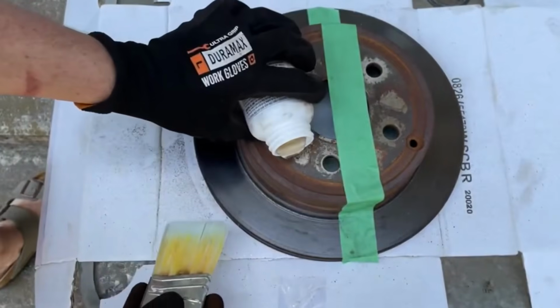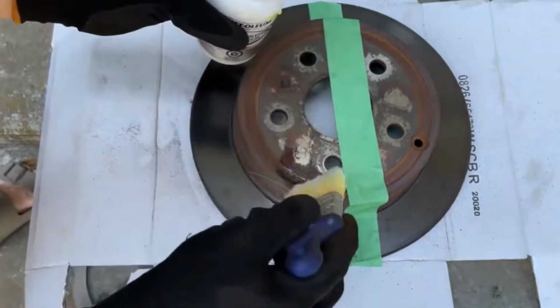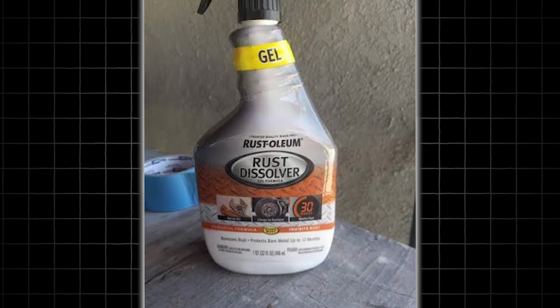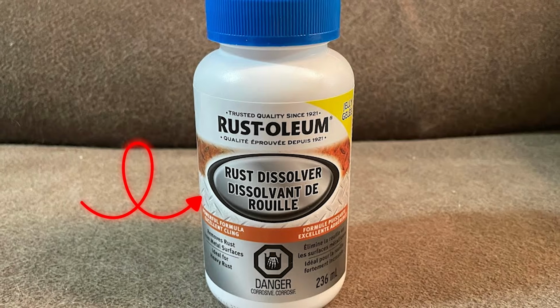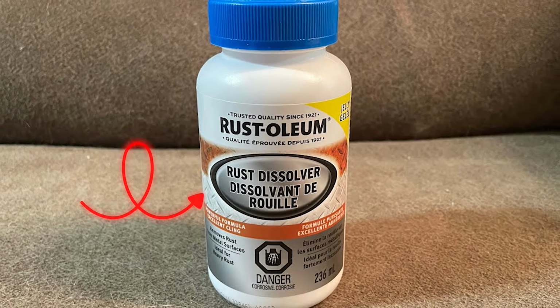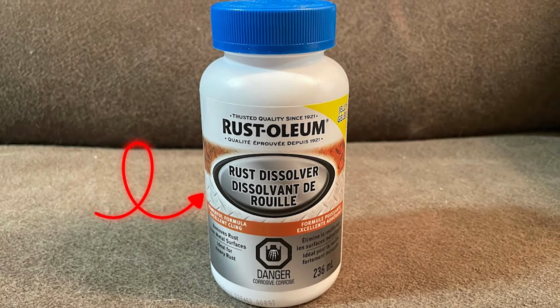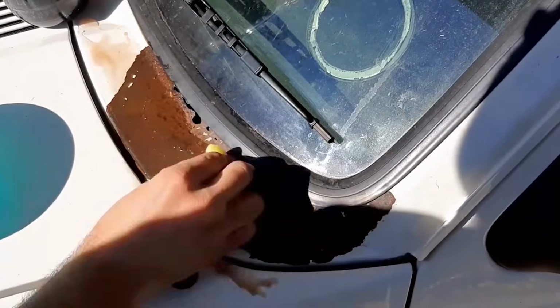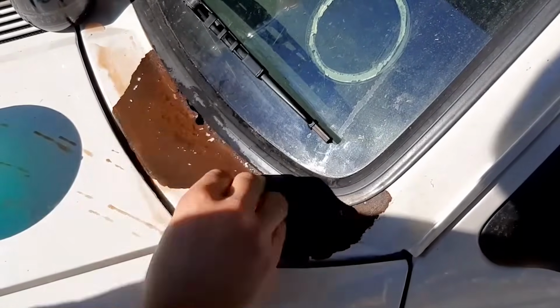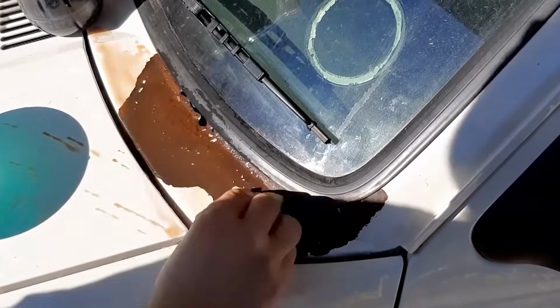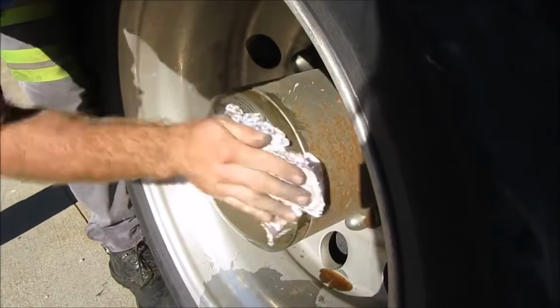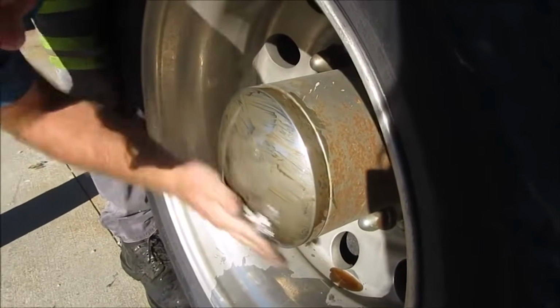Initial results at the 30-day assessment point appeared promising. The 3-month assessment revealed the limitation. Phosphoric acid conversion products convert the surface layer of rust that the formula contacts. They do not penetrate into pitted rust below the surface layer. On frame steel with moderate pitting, the surface converts to iron phosphate while the rust in the pits continues progressing